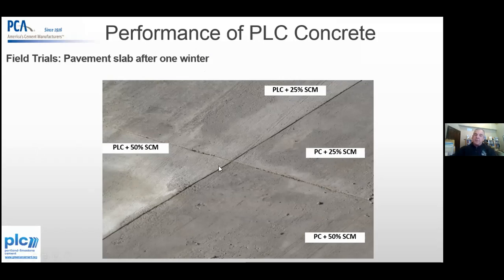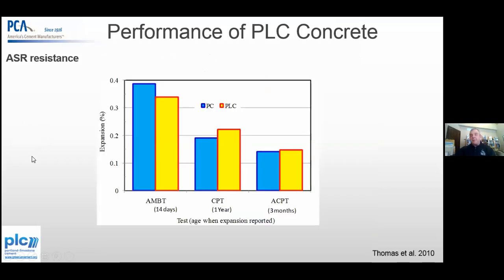Portland cement, and they basically just abutted against one another. Portland cement with slag, or I believe it was fly ash here actually. No, it was slag. Sorry, Portland cement and 50% slag, PLC and 50%, PLC and 25%, and PC and 25%, and no scaling issues whatsoever. Anybody who's been to Montreal knows they get freezing rain, they get cold, they get snow, and it can be pretty nasty sometimes. And then ASR resistance, you get good mitigation in your concrete prism tests, your accelerated mortar bar test, and your accelerated concrete prism test, which they were trying to promote at one point. It's still in the research stages, but equivalent performance in ASR as well.